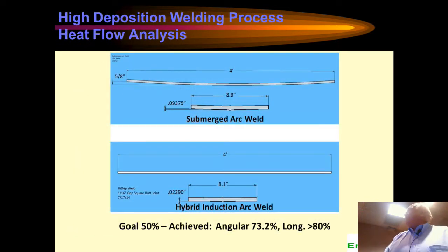On the 3/8, I wanted to compare it to, so the Navy asked us to use SubArc as a benchmark because that's the process they're using for these thick steels. So you'll see here the top is the submerged arc weld and the bottom is our high deposition weld. In the longitudinal dimension, the top diagram in each one of those pictures is about a 4-foot section, and the subarc raised up about 5/8 of an inch on each end, and in the longitudinal dimension we didn't see any distortion. Nothing was measurable.